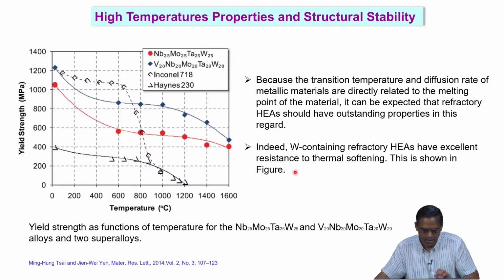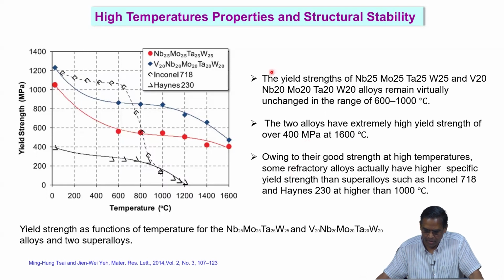So, these results clearly demonstrate the structural stability, and what you are witnessing here is the yield strength of these alloys remain virtually unchanged in the temperature range, especially between 600 to 1000 degrees centigrade. So, this plateau we are talking about, though they have extremely high yield strength over 400 MPa at 1600. Even at 1600 you have the difference of about 400 MPa compared to this conventional alloy which softens significantly. Owing to their good strength at high temperature, some refractory alloys actually have higher specific yield strength than the superalloys, such as Inconel 718 and Haynes 230 at higher than 1000 degrees centigrade.